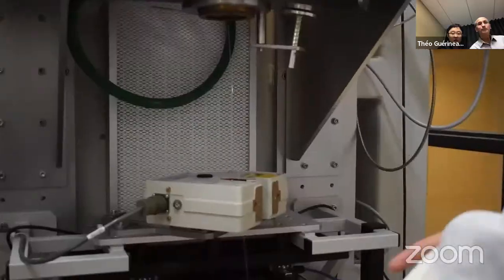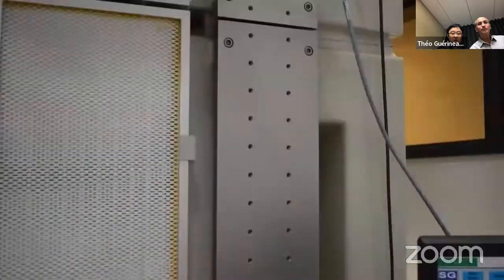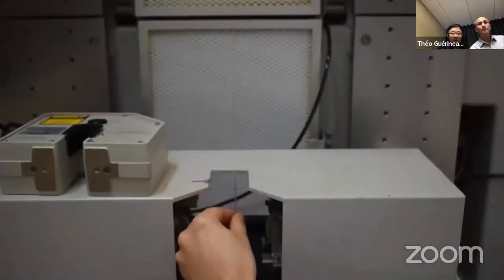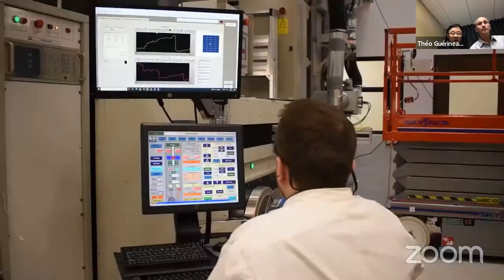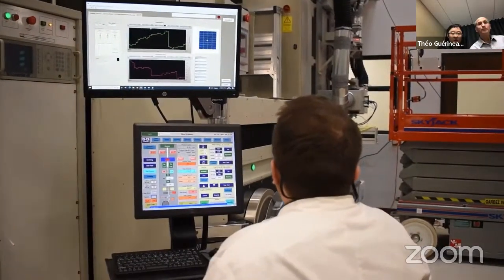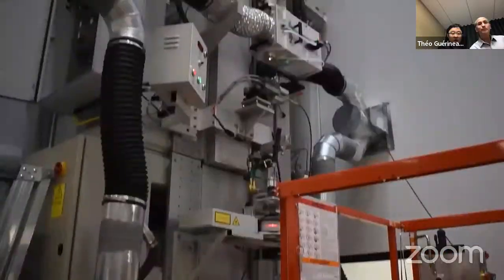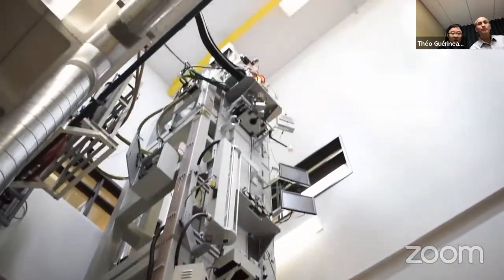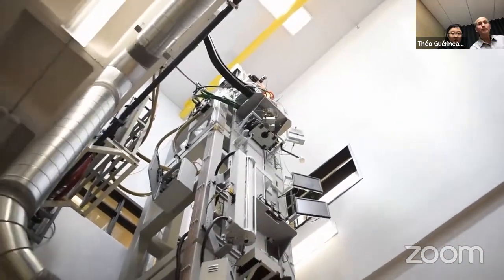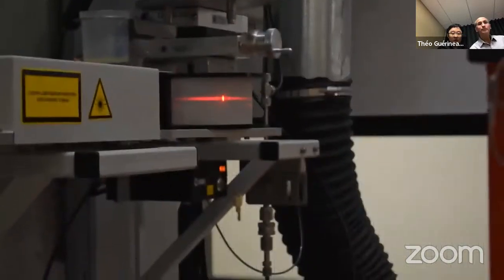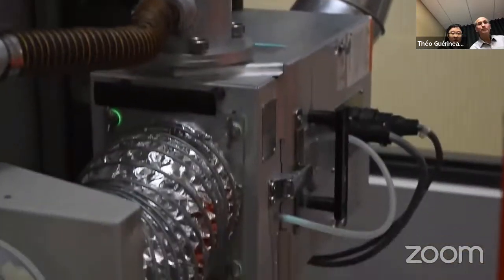Here, we observe the first drop flowing at the beginning of the drawing. The filament that comes just after it will form the optical fiber. The fiber diameter is closely monitored along the process and controlled by optimizing the temperature and drawing speed. A double polymeric coating is applied to protect the fiber, improving its mechanical resistance.